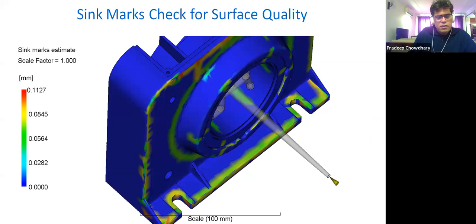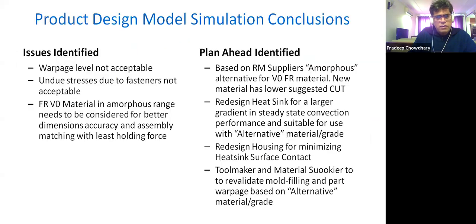Further, we got sink marks in certain areas going up to 100, 120 microns with this material. So a lot of red flags were raised with the design analysis. Warpage levels were not acceptable. Stresses were not acceptable, fastener sizing wise.